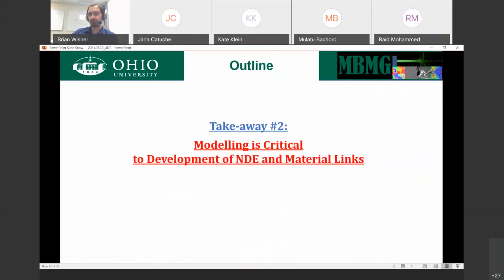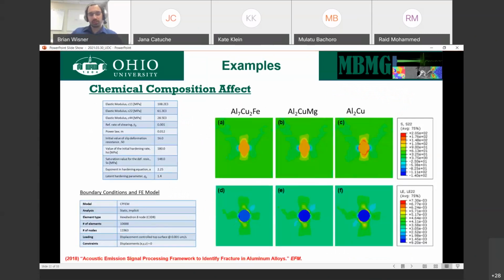Can we detect that? Well, first, let's figure out, to some extent, what we might be interested in detecting. So to do that, we're going to do some modeling. What you see here, in addition to the details of the model, is an example of a crystal plasticity finite element simulation that has a single crystal, the green, of aluminum, with a particle embedded in it. The properties of that particle, in this case we're assuming perfectly round, is altered to simulate the properties you would expect from an aluminum 7 copper 2 iron particle versus aluminum copper magnesium versus just aluminum copper.